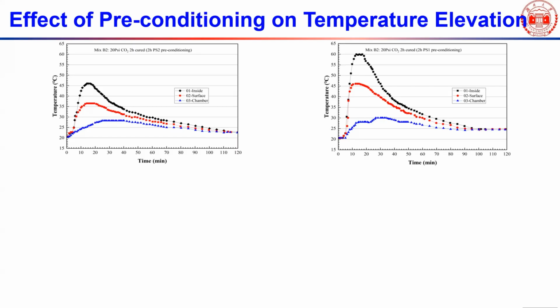So you can see at almost 15 minutes, in this 5-liter container with 4 samples, the temperature here reached about 45 degrees C. And the next one, the right one, even reached over 60 degrees C. You can see how much heat, even within 15 minutes. Because if you really measure the carbonation degree within 15 minutes, it is also relatively not that high.